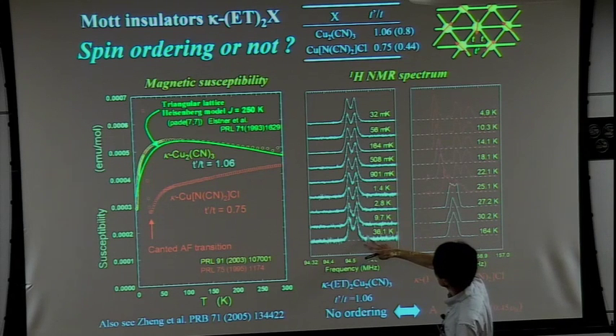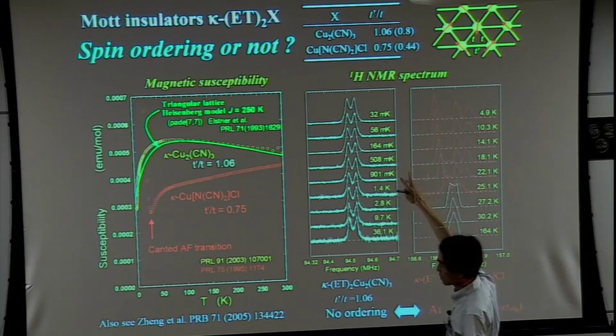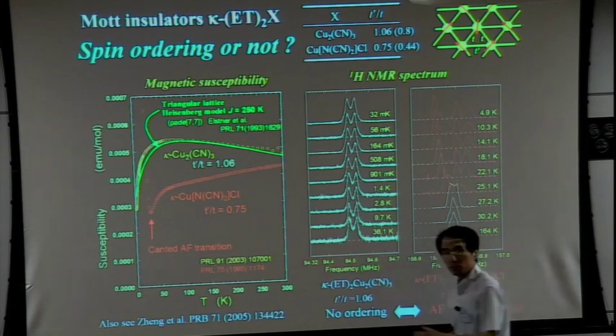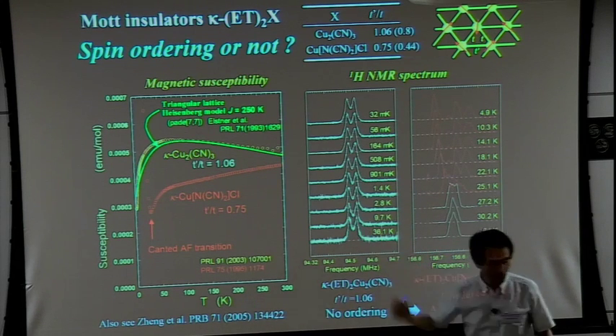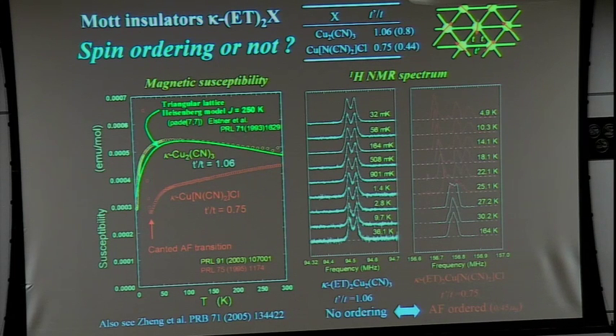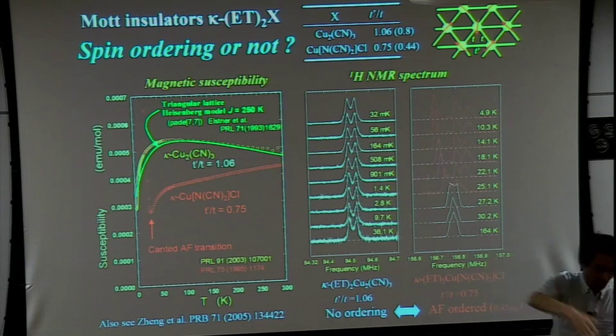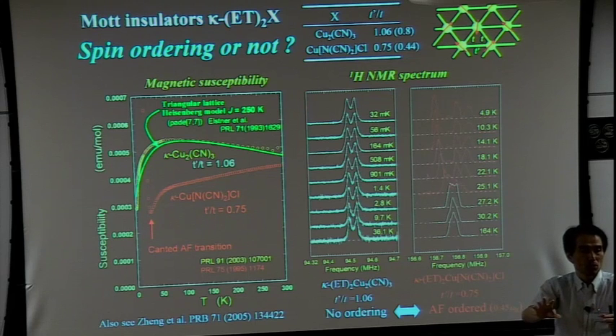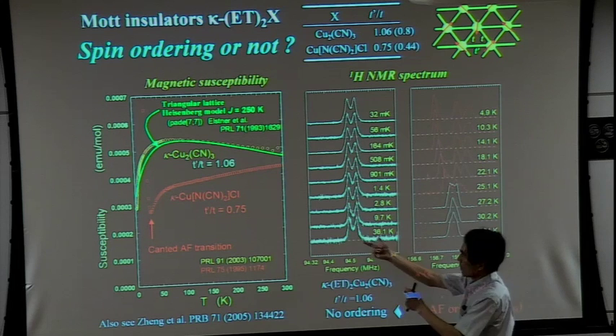However, please take a look at this spectrum: no change down to 32 millikelvin. This doublet, the double peak structure, does not matter—it's due to dipole coupling between two neighboring proton atoms on the edge of the molecules. This dipole coupling gives a splitting, and this splitting depends on the magnetic field direction. In some directions, this splitting vanishes; this angle is called the magic angle. But in these experiments, we are unlucky because the field angle is just at the magic angle, so there should be no splitting, yet in this case the peak doublet is clearly seen.